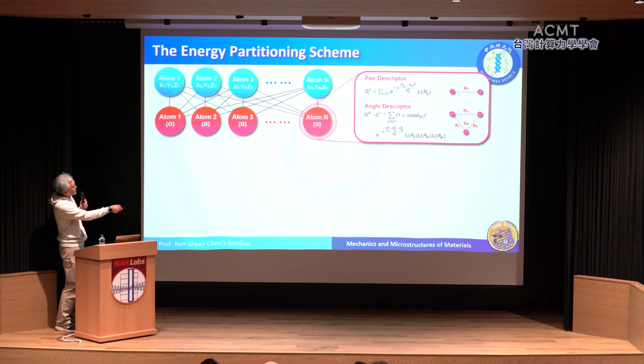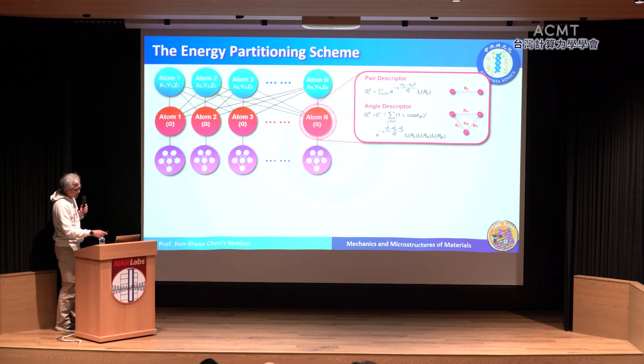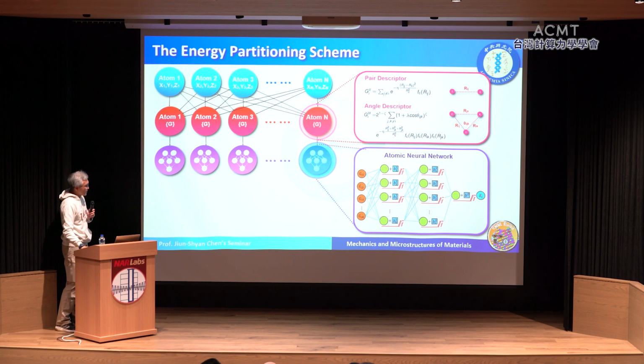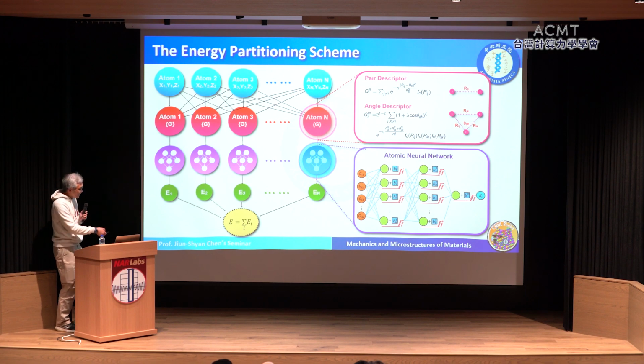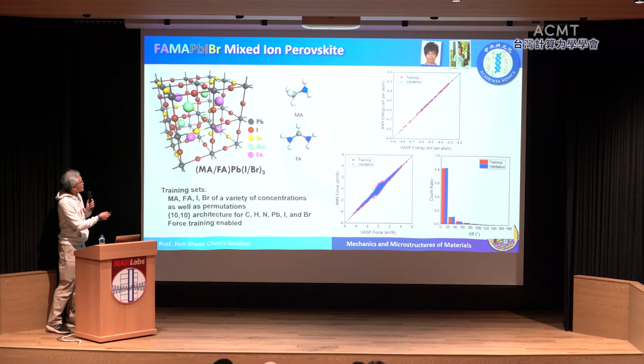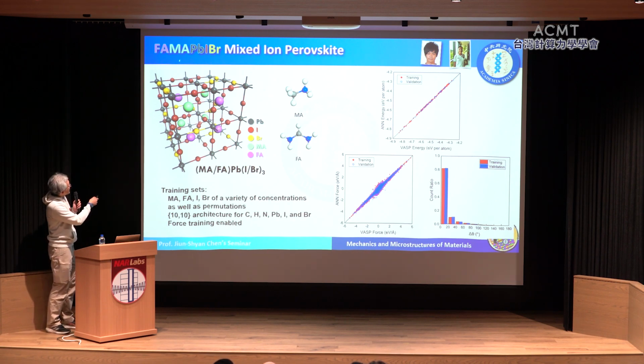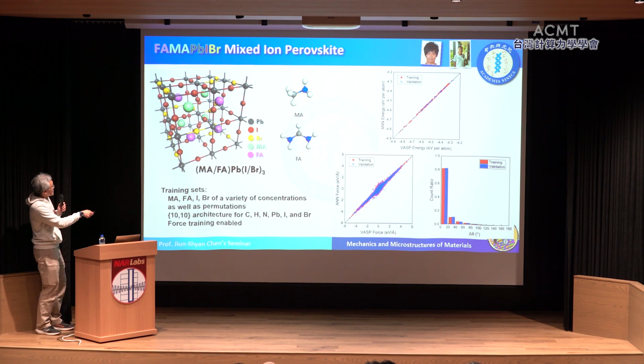So basically, we include both the pair interaction and the three-body interaction, and then we let all these feature vector embeddings pass through atomic neural networks, and then we have the total energy of the whole system. We use this scheme to train a neural network model of this FAMAPbBr, and as you can see, this is a very complicated mixed-ion perovskite. These are done by my former student and my former postdoc. MA actually looks like this, and the FA actually looks like this.